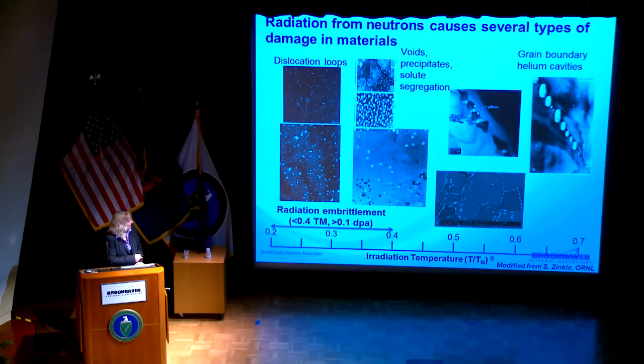However, at higher temperatures, you can get additional types of damage. So you can see voids, solute segregation, and void swelling. You can actually get cavities on the grain boundaries that cause macroscopic swelling of the material. So all of these areas and all of these types of radiation damage are things that have the potential to be studied with X-rays.